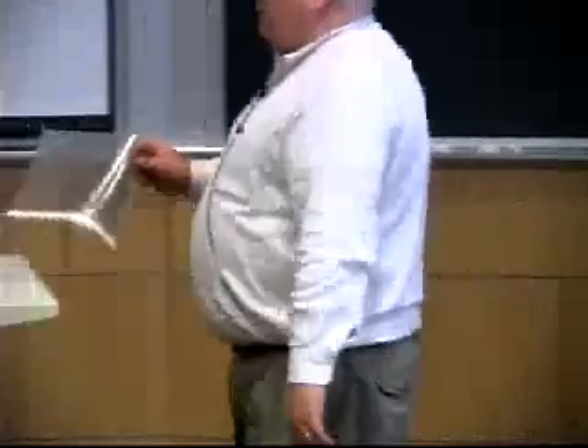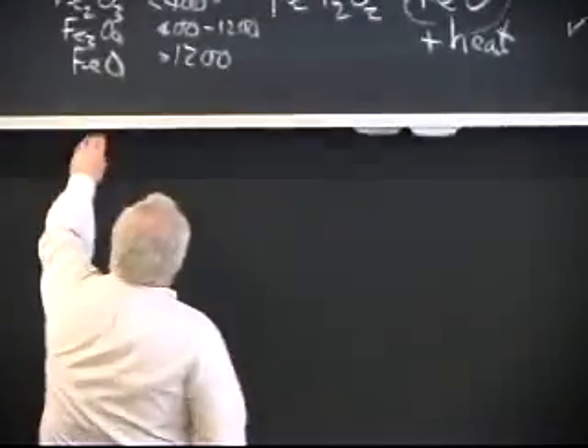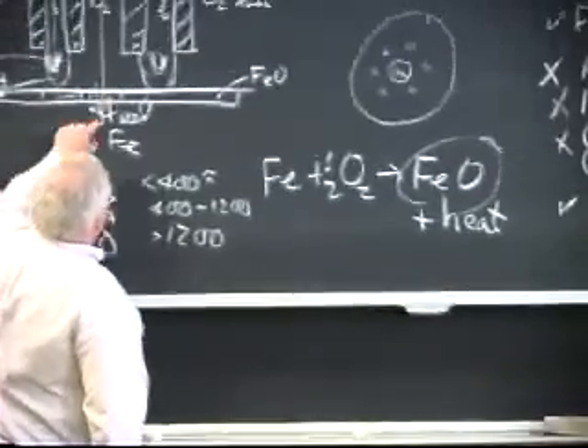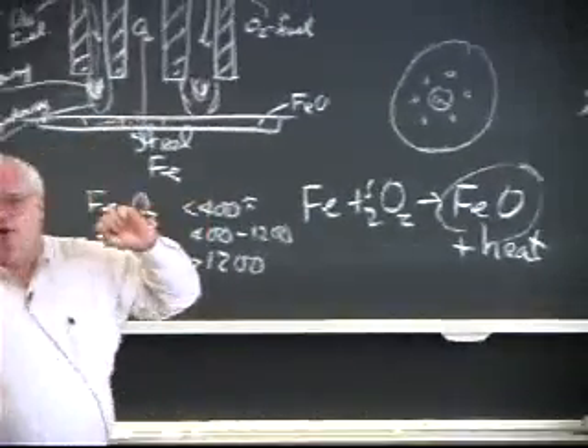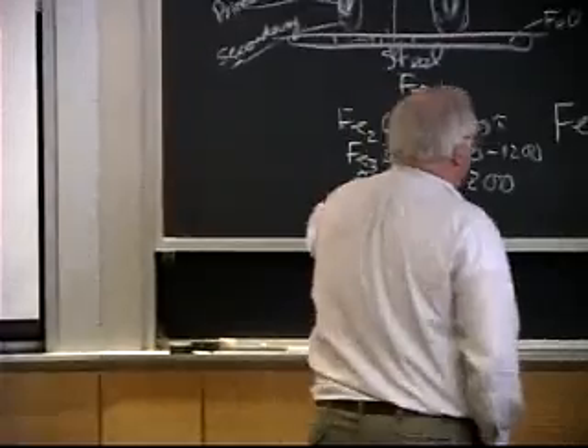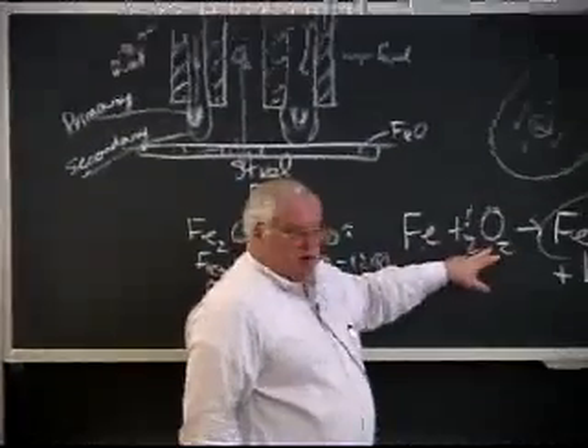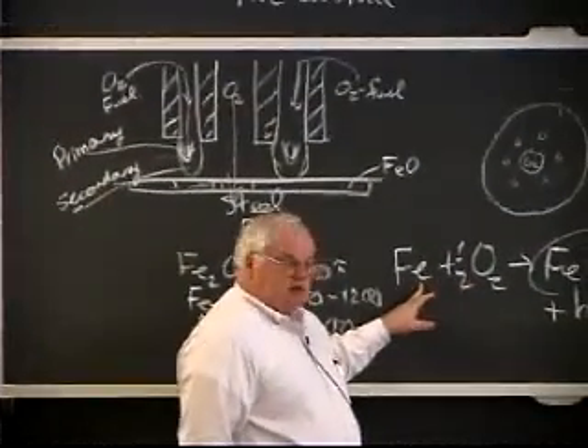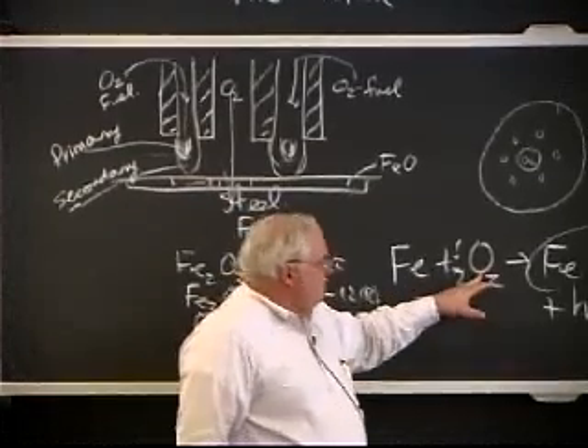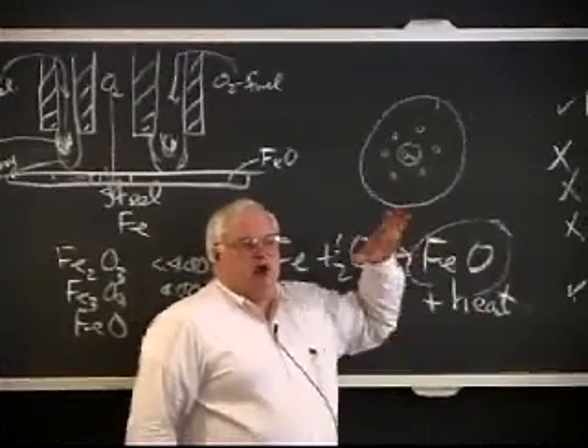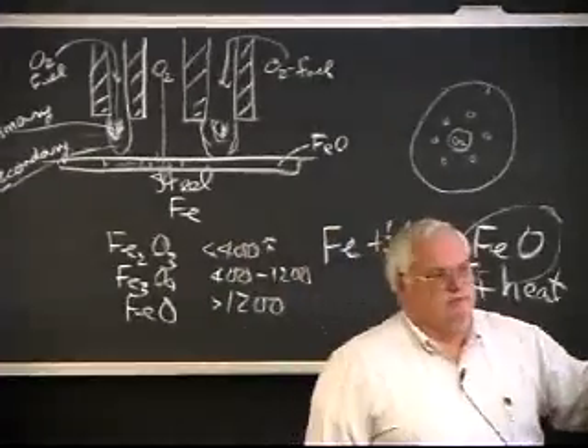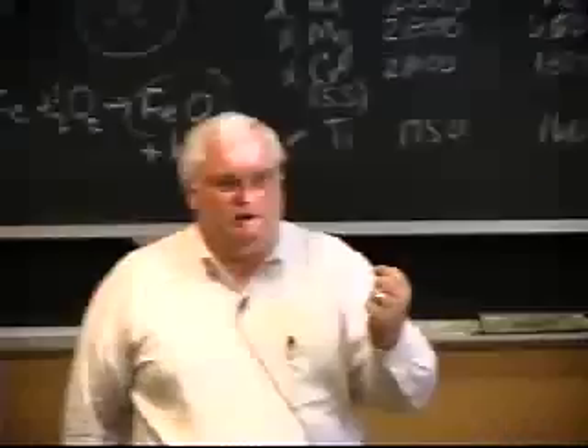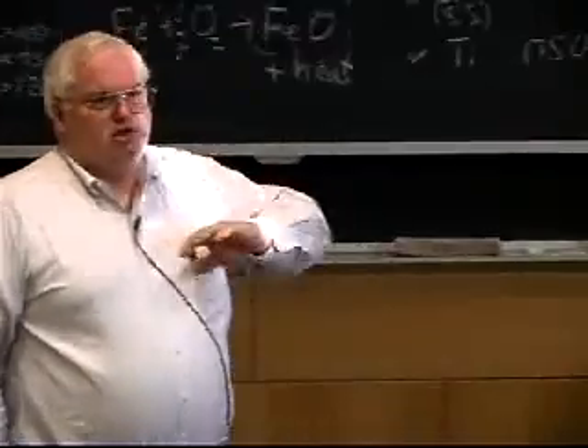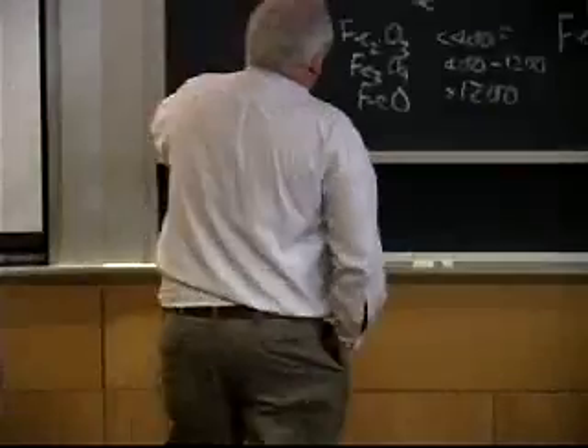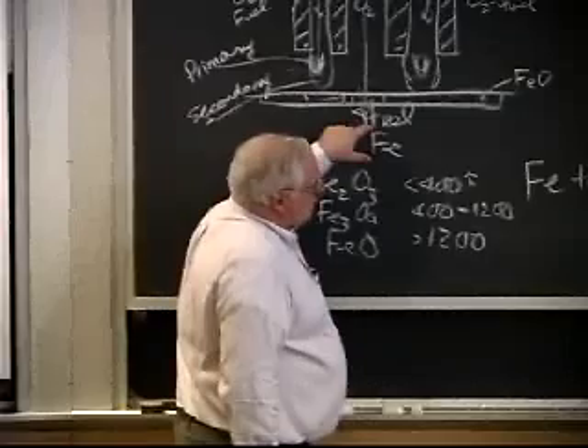Now it turns out that the reason you can get such high rates of effective heat transfer in here is because I have no gas boundary layer, in theory. What happens to the gas? Well, the gas in here is pure oxygen, this is a solid, this is a gas, and it goes to a liquid. So I condense my boundary layer to a liquid. The boundary layer is consumed by the reaction and forms a liquid, which is blown away by the jet of oxygen coming in.